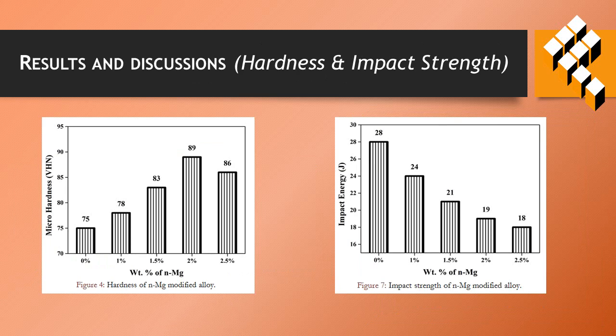Figure 4 shows the micro-hardness of the nanomagnesium modified alloy. The hardness of the nanomagnesium modified alloy increased from 0 up to 2% due to the brittle phase of the nanomagnesium particulates, whereas at 2.5% the hardness was reduced due to the inter-dislocation movement.